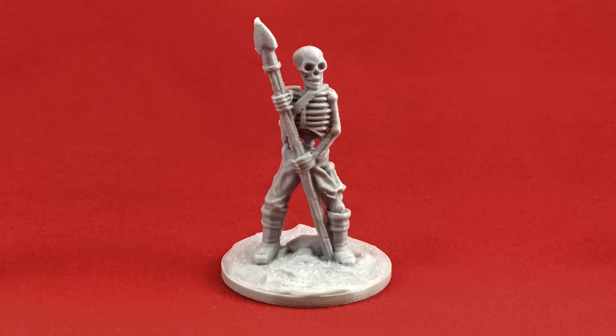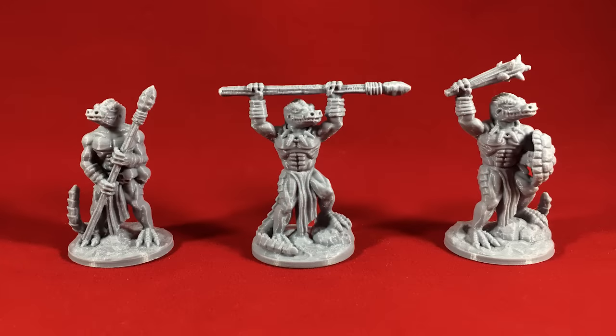Now, we've already established that the thinnest points of the miniature, like weapons and ankles and arms, aren't going to be affected one way or the other by how much infill you use in your miniature. They're just going to be affected by the width of the walls at 28 millimeter scale. So you're not gaining anything there as far as strength. And those are going to be the first things to break. What you are doing by adding more plastic than necessary to the miniature is you are increasing that kinetic energy of an impact. You're creating more mass, which when the miniature falls is going to create more energy for the impact and a greater chance of breaking it. So again, no reason to have 100% infill, but a lot of reasons not to.